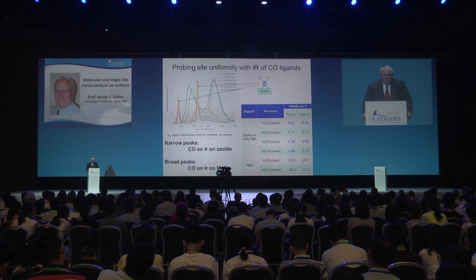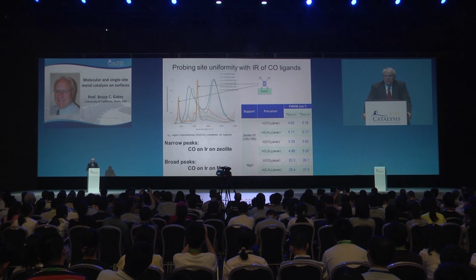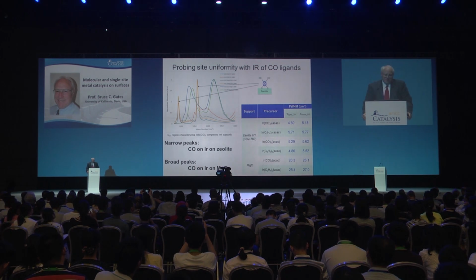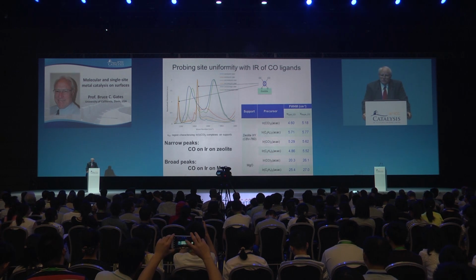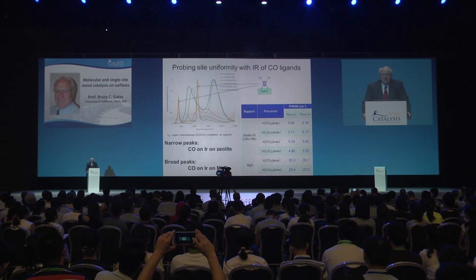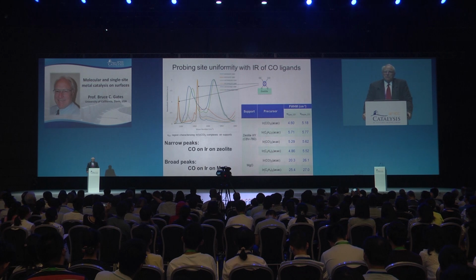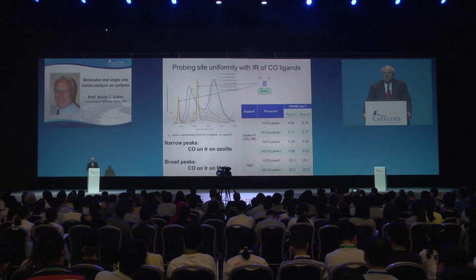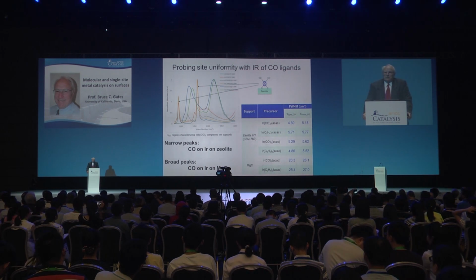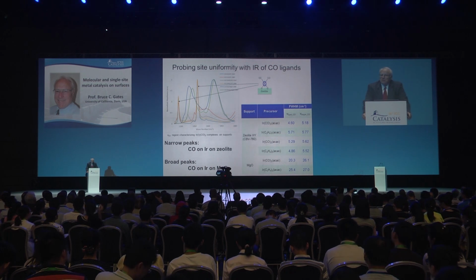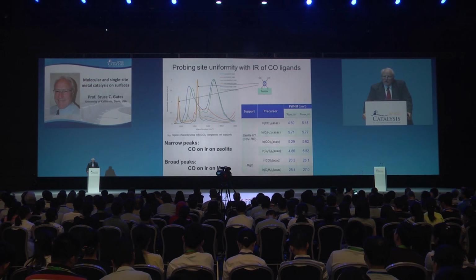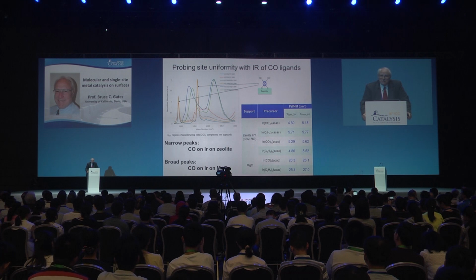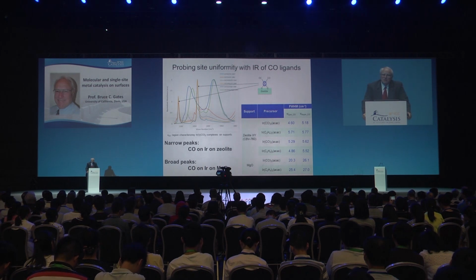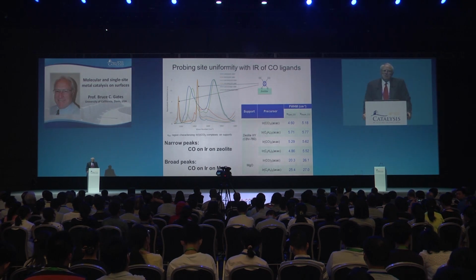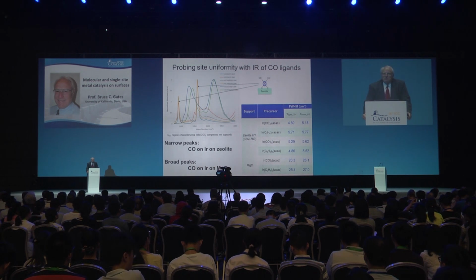In contrast, if the support is a metal oxide, here it's MgO, various MgOs, then the bands are much broader. The sites to which the metal is bonded are a smear of sites, not one site. And so we have a quick, easy, inexpensive diagnostic of degree of uniformity by using carbonyl ligands on the metal to probe the surface species.